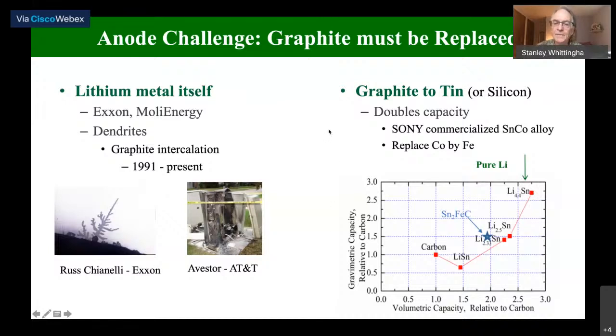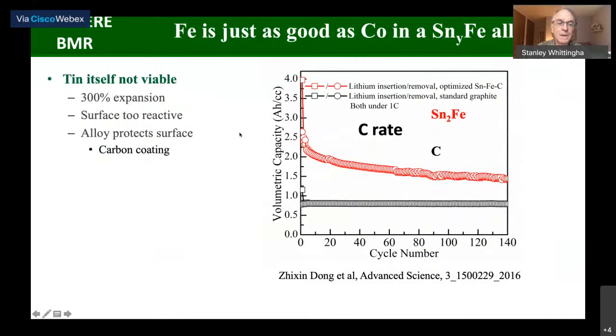In 2005, Sony had commercialized a tin-based anode. We found out that was in fact a 1-to-1 alloy with cobalt. Obviously, cobalt's too expensive, so we set out to replace it by iron. And I show you some of the data here. You cannot use tin itself because it expands 300%, which means it eventually decrepitates into fine powder, and its surface is too reactive. So the surface keeps reacting with the electrolyte. So by making this alloy, we're protecting the surface, and it's also encapsulated in some graphitic carbon.